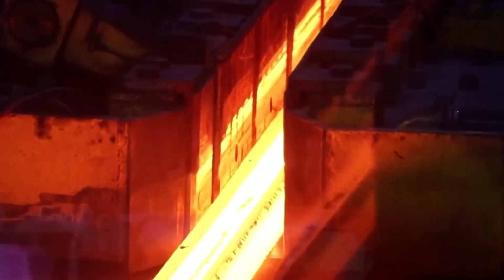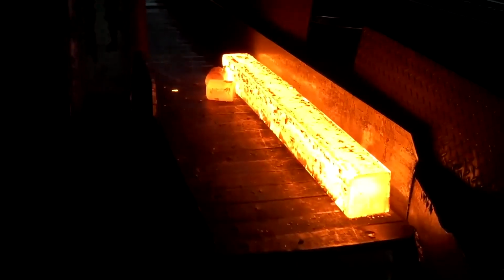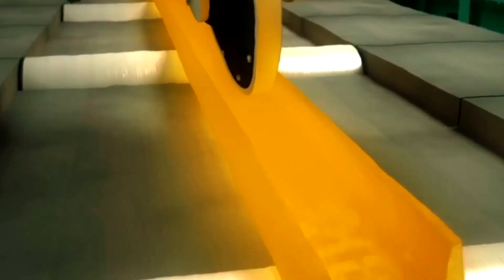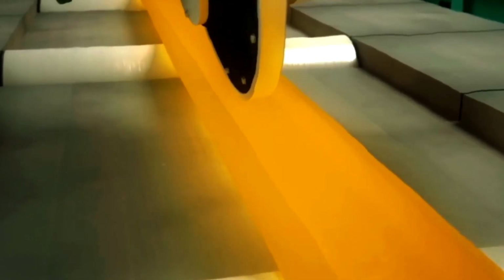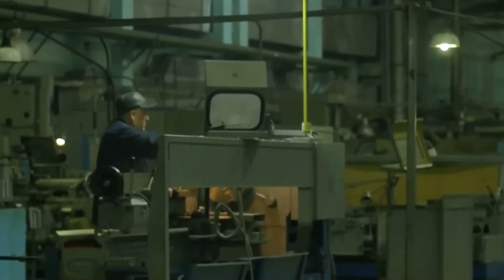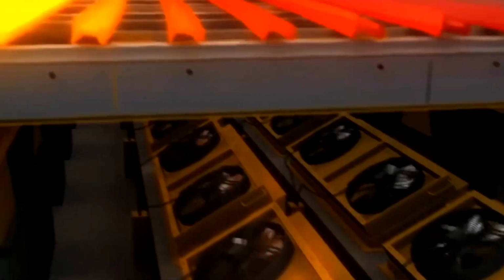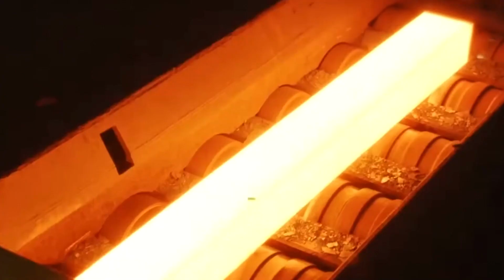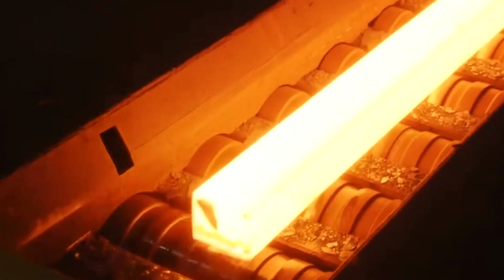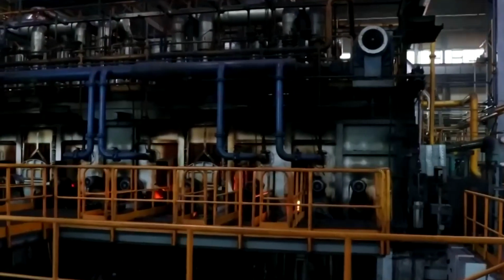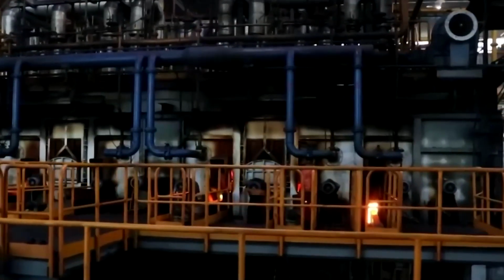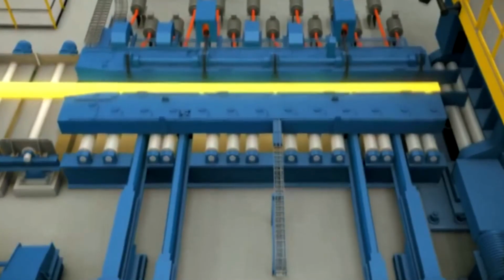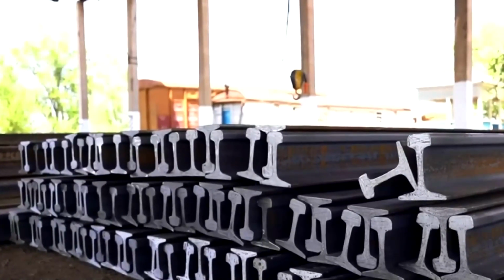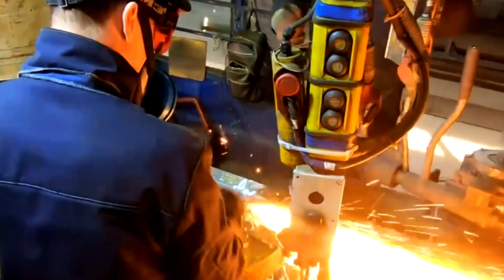Inside these fiery caverns, the temperature is carefully held above 2200 degrees. High-powered burners work in concert with infrared sensors, which constantly scan every point on the billet surface, ensuring the steel never cools too quickly. Even a minor drop in temperature could cause the surface to harden, inviting cracks or deformities during the shaping process. After this thermal stabilization, the billets are conveyed to the rolling preparation line.